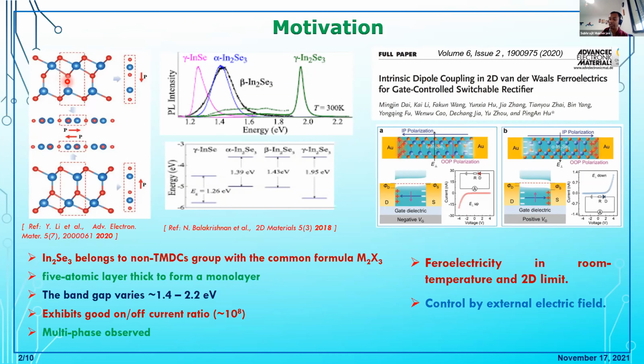So why are we working on indium selenide? Because indium selenide has a unique structure. First, it has many phases, so it offers a phase dependent band gap. According to your application, you can choose what type of material you need. And most interestingly, the alpha phase indium selenide is a ferroelectric. It also offers intercoupled ferroelectricity. That means it has in-plane polarization and also out-of-plane polarization, and you can control one of them by controlling the other.